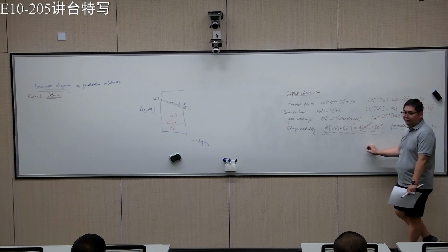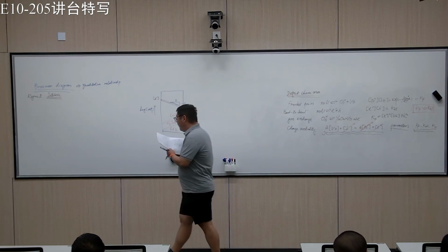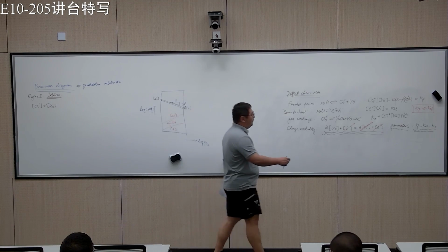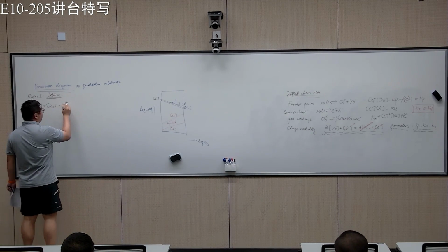We say we have a majority of this one and this one rather than electrons and holes, because we assume that Kf is much larger than KEL. You'll see that in a minute. So the simplified condition is that the oxygen vacancy concentration is the same as the oxygen interstitials. These are determined by Kf, so they are the square root of Kf. No problem with that, right?